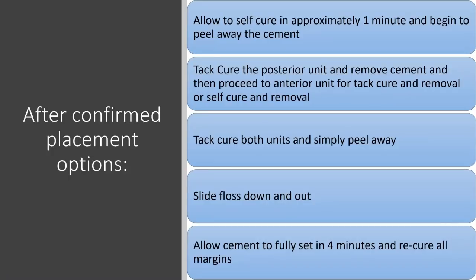You could simply allow it to self-cure, and in about 1 minute, you would begin peeling away the cement. But I don't want to wait a minute. So I tack cure the posterior unit, and then you could remove the cement because you want to make sure that's the area you're trying to control the most because it's near the back of the mouth, more saliva. So you could tack cure, remove the cement, and then proceed to the anterior. Or you just tack cure the posterior and tack cure the anterior and start peeling away, which is also easy with just 2 units. Once you've peeled it away, then you're just going to slide the floss down and out.